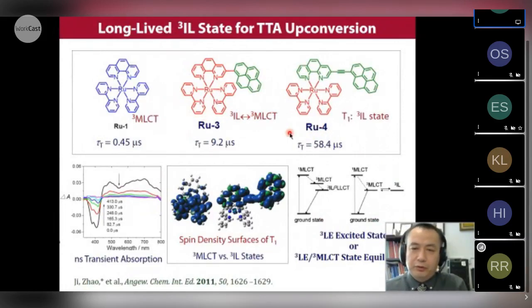So firstly, we studied a few complexes showing much longer triplet lifetime than this model one. This one, the lifetime is very short, only 0.5 microseconds. But for these two, we observed very long triplet lifetime.